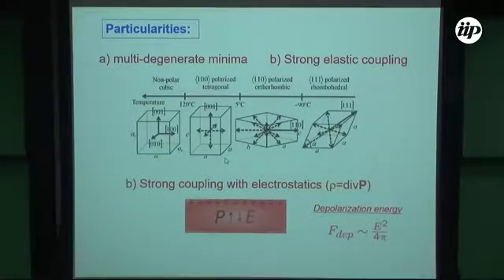First of all, as I told you from the beginning, what is most important for industry, for technologies, and also much easier to obtain as samples, is usually a cubic perovskite, which has different directions of the displacement of the central titanium atoms. Depending on the material, the temperature and many other factors, one can have, for instance, displacement up-down. In this case, we shall have six equivalent directions, or we can have more equivalent directions, because we can have the so-called orthorhombic phase when the central atom is displaced in the direction of a non-principal diagonal, and in certain cases the displacement is along the principal diagonal, so it will be 8 equivalent directions.